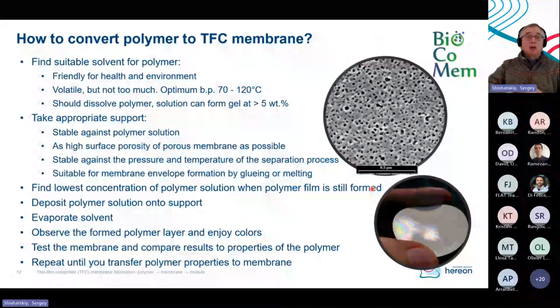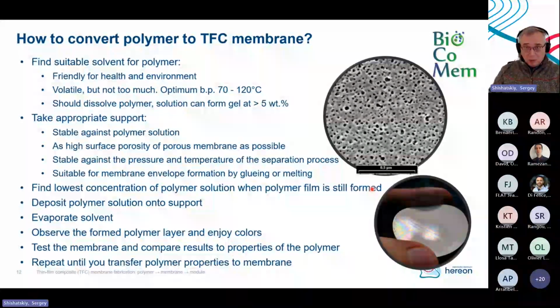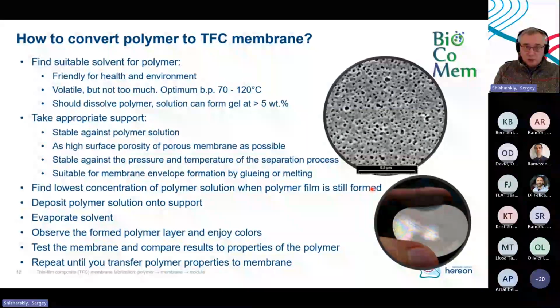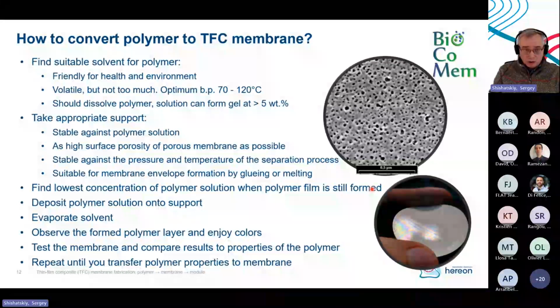And now, how to convert the polymer to the TFC membrane? First thing, you need to get a suitable solvent for the polymer. It should be friendly to yourself and to the environment, so you should not die when you use it. It should be volatile, but not too much. So the optimum boiling temperature is between 70 and 120 degrees. If it's lower, then you will have very strong cooling of the membrane surface, and you will have condensation of water from the air.